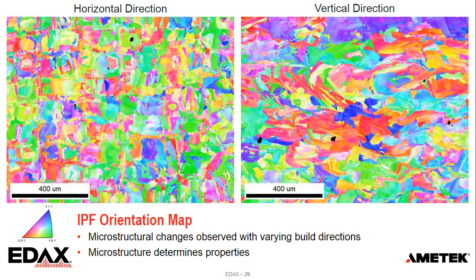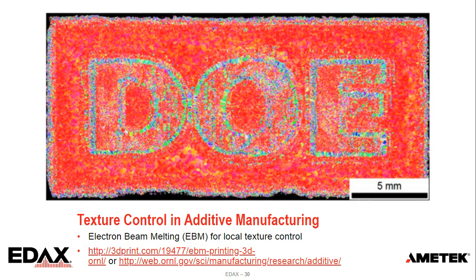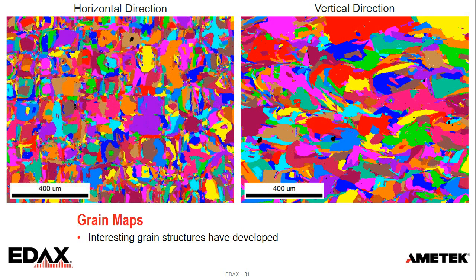And this is a really good example from Oak Ridge National Lab a few years ago. This is electron beam melting of a nickel superalloy, but they varied the build conditions to actually write a DOE into the microstructure. I just think it's a really cool example of the idea of controlling localized properties in additive manufacturing, which I don't think you could do as easily through more traditional means of fabrication. And this just shows the grain maps of those horizontal and vertical directions, again with randomly colored grains.